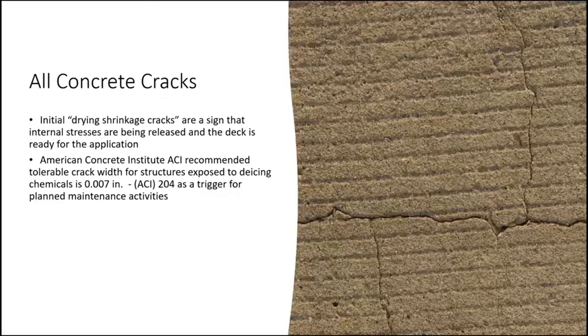We'll start by considering why even look at a protective deck overlay treatment. And it starts with the fact that, personally, I don't know if I've ever seen a bridge deck that didn't have at least some initial drying shrinkage cracks. If you look at American Concrete Institute ACI 204, it says that if you have cracks wider than 7/1000 of an inch exposed to de-icing chemicals, then that should be some sort of a trigger for maintenance activity, meaning that you don't want moisture and de-icing chemicals and things like that going into these types of cracks.